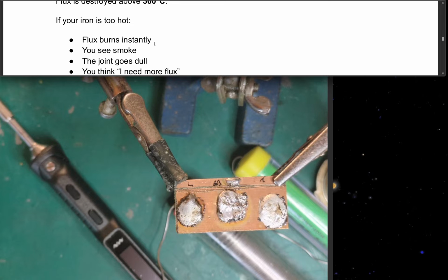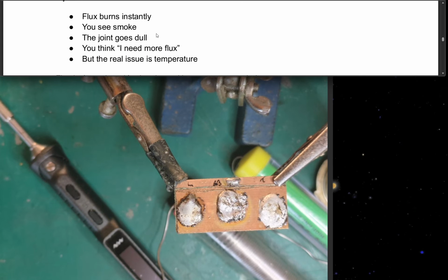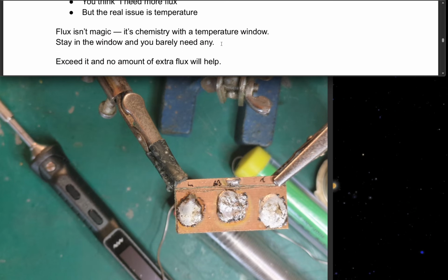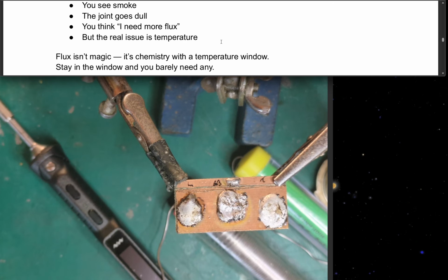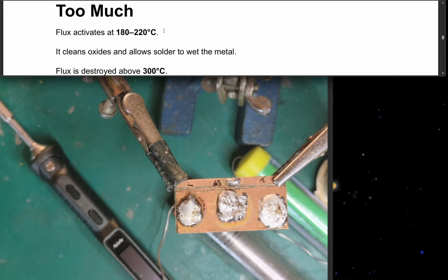So if your iron is too hot, the flux burns instantly, and you see smoke. The joint goes dull. You think you need more flux, but the real issue is the temperature. Flux isn't magic. It's chemistry with temperature windows. Stay in the window, and you barely need any. So you hardly need any if you just stay within this temperature here. And like I say, when we later look at the melting temperatures of solder, you'll find that the solder melts within these temperatures also.